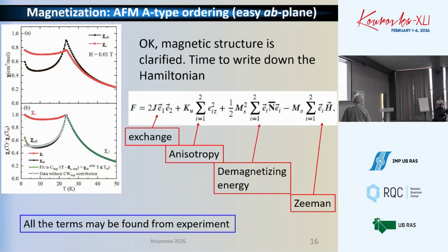Now we know everything. We can write down the Hamiltonian, but instead I write almost the same in the free energy, which is the coupling constant, exchange, and I don't specify here the largest exchange in plane. I will not be talking about the in plane. Still, here is also the coupling in interplane, some anisotropy, which I explained how it can be extracted. The less important are demagnetizing energy, shape-dependent energy, Zeeman energy, which is also quite unimportant here. So everything can be found from experiment without going to Brookhaven or Oak Ridge.